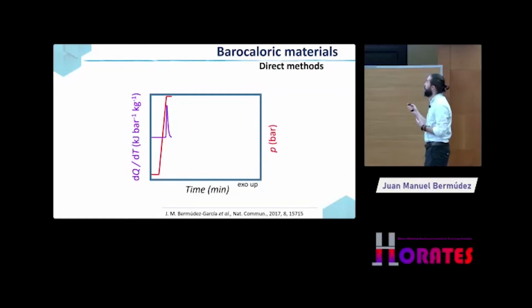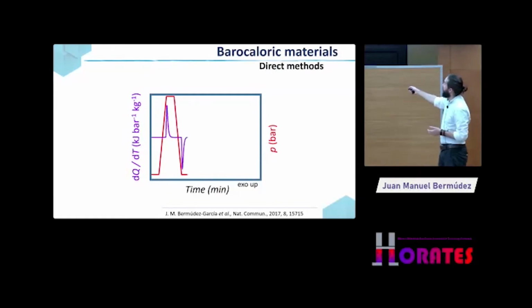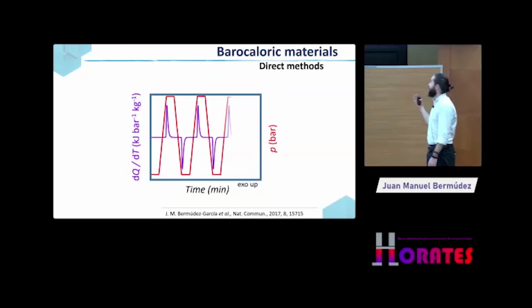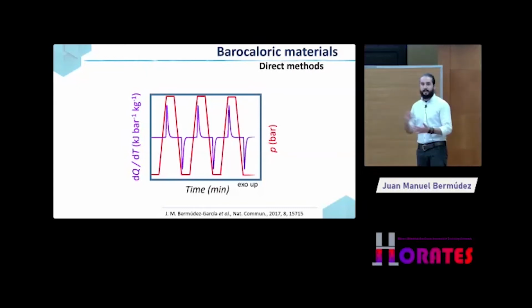You do that as well under depressurization, and you have the reverse transition. And you can do that over and over again in order to test the stability of your material over time, okay? But as I said, this is the less common characterization that you can find in the literature, because those calorimeters are not very common.